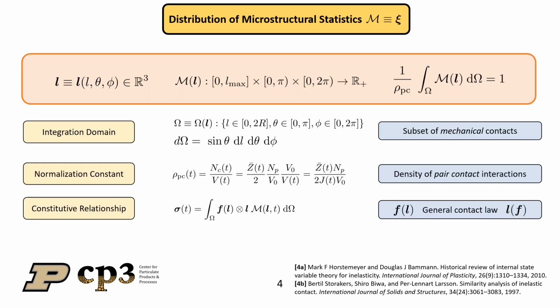We now define a distribution of microstructural statistics M. M represents the distribution of branch vectors L that constitute all the grain pair contacts in our system. We consider an integration domain that is the subset of mechanical contacts that cause contact forces, which in the case of a monodispersed packing ranges up to 2 times the undeformed contact radius.